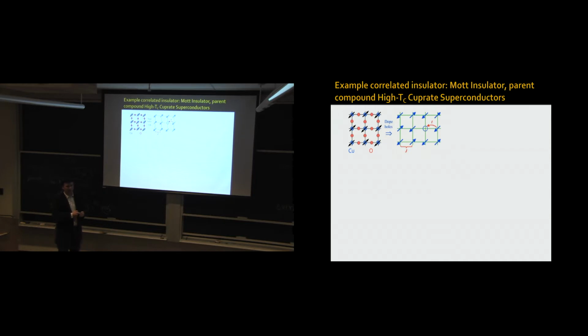In these high temperature cuprate superconductors, you have these copper oxygen planes where in the copper atoms you have a single orbital and you can put an electron there with spin up or spin down. And in the parent compounds of these materials, if you don't dope them, you have exactly one electron per site. And the strong interaction between these electrons leads to localization, to a Mott insulator behavior, where electrons are just stuck in there.